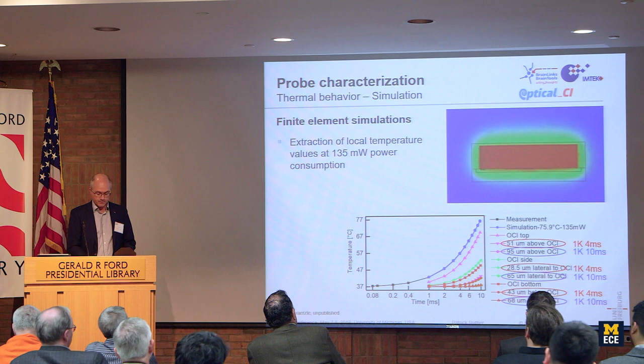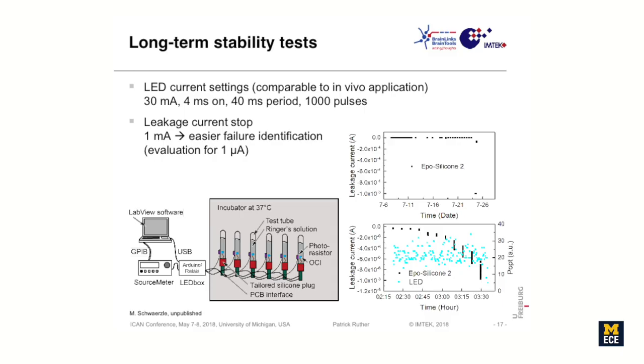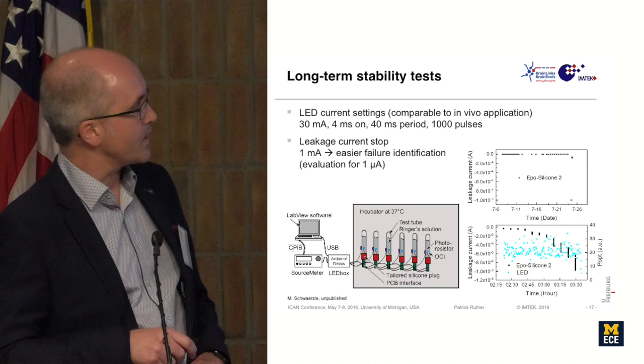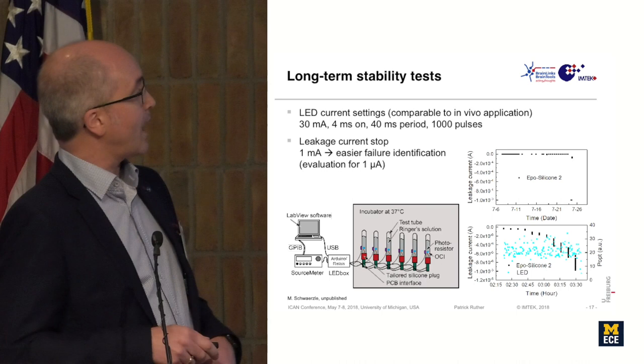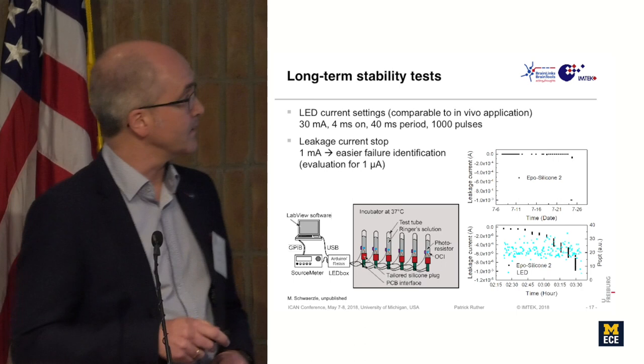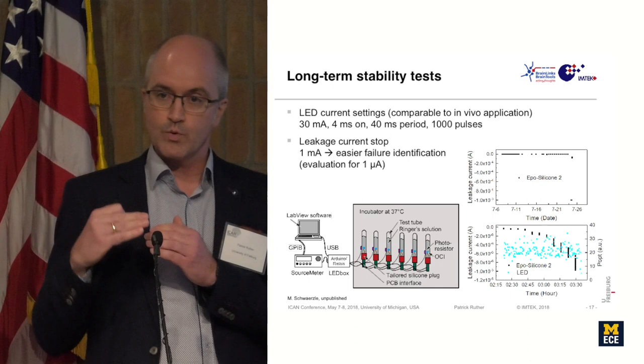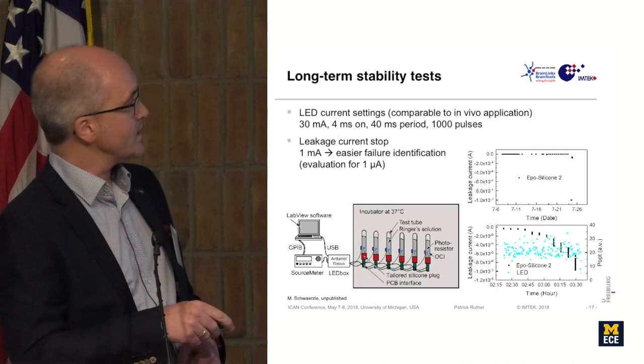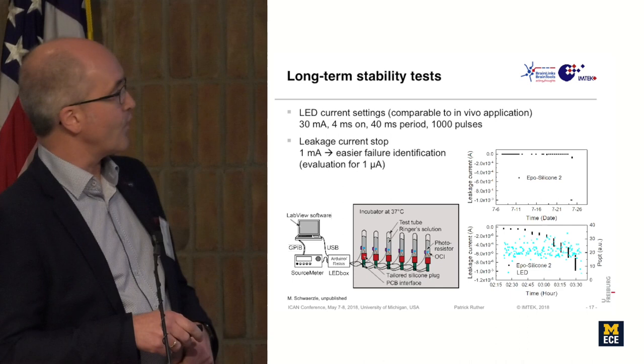The other question is, when do these probes fail? Unfortunately, I cannot tell you they always fail after 2 weeks or later. No, that's at the moment not predictable. But what we see here is a typical test scenario where we operate the LEDs with 30 milliamps, again a high electrical power, 4 millisecond long pulses, 10% duty cycle, and we do 1,000 pulses, which means 1,000 times heating up, cooling down, so mechanical stress in the device itself. And once this is done, we make a leakage measurement, reverse biasing the LED and checking for the leakage current.